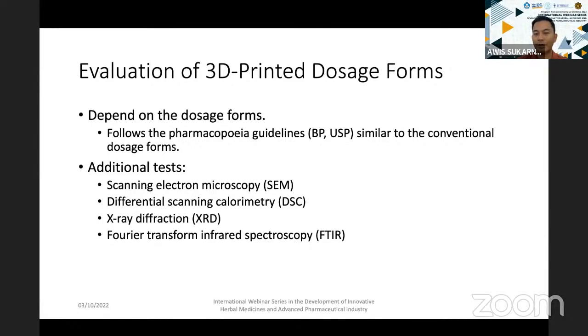Because sometimes after you 3D print it, you find that the release profile, for example, is faster. And then after you scan it using SEM, you notice that actually it's because your sample is very porous. So that's why the release profile is faster compared to the normal one.